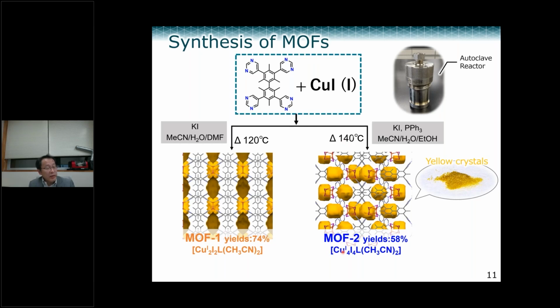The chemical formula is Cu4I4L and acetonitrile. In this case, the yield is 58%, which is quite good. Actually, in both cases you always obtain a mixture. Unfortunately, we obtained a MOF-1 and MOF-2 mixture.